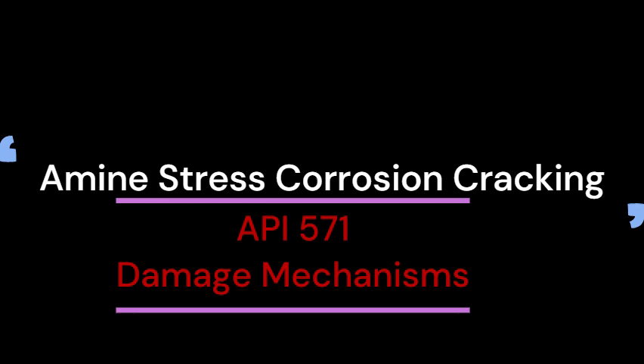What about ultrasonics? UT is used everywhere. Can it find amine SCC? UT, like standard shear wave UT or the more advanced phased array, PAUT. It's useful, definitely. Mostly for sizing cracks once you know they're there, or for monitoring if they're growing over time. But not for initial detection.